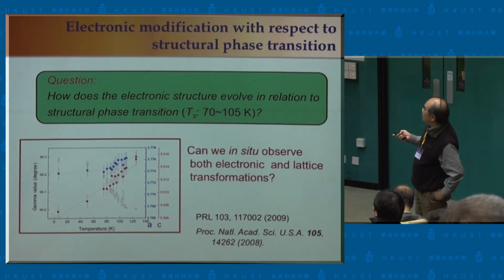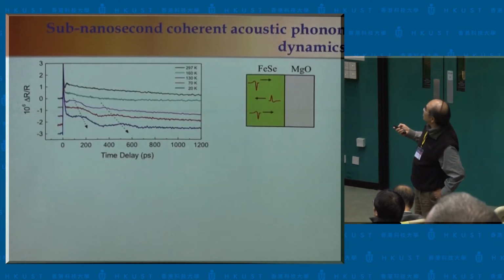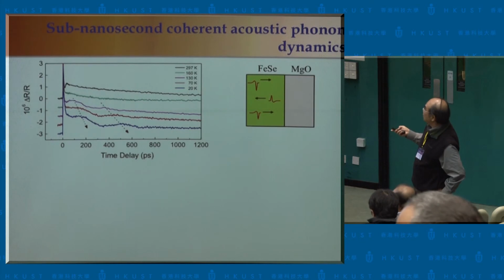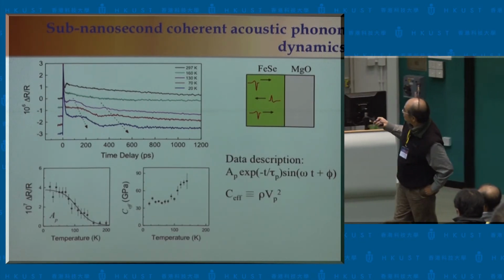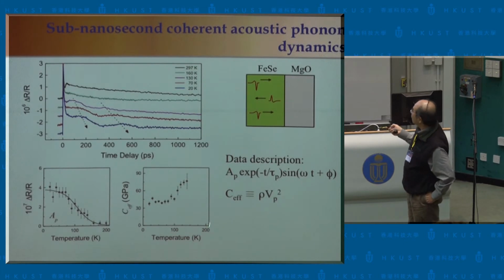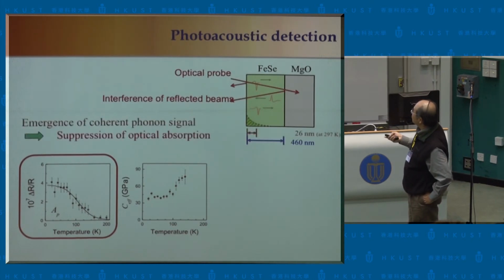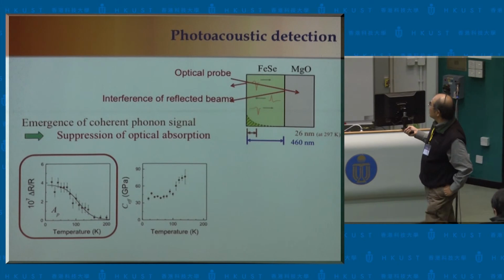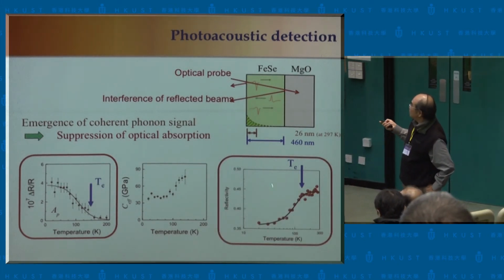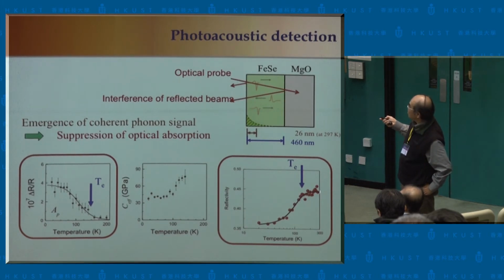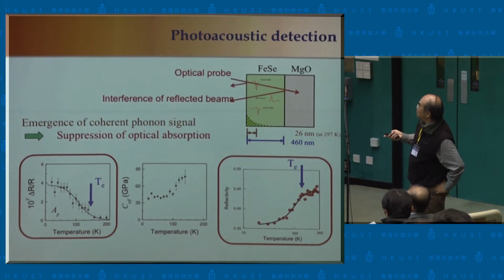Well, then the question is, what can the low temperature distortion give us from this optical measurement? We can study this using sub-nanosecond coherent acoustic phonon dynamics. This is a simple experiment, and I'll just tell you the result. Around 90 Kelvin, we did see a stiffness, which is associated with the structural transformation from this optical measurement. This very clearly shows that the onset comes out of this kind of modification and then ends up with this structural distortion. So there's a close correlation between these two.